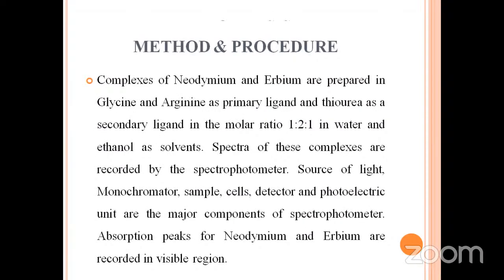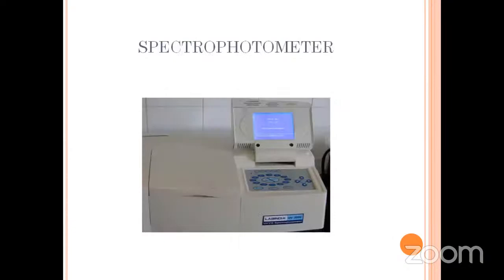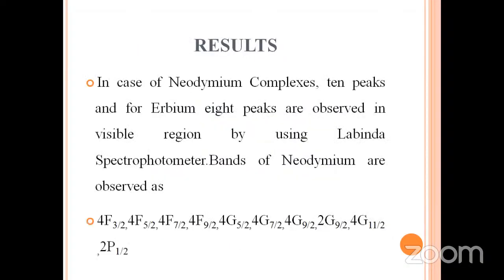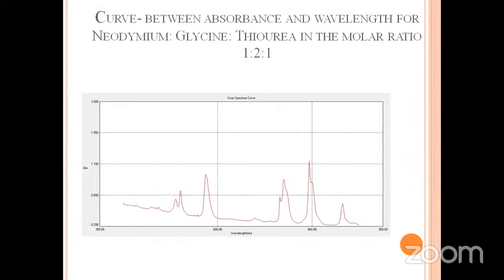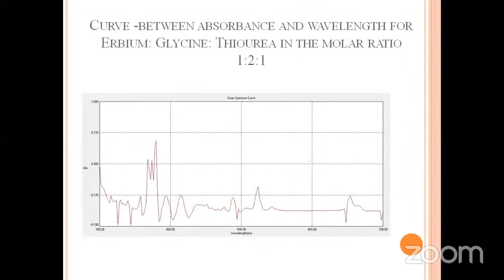And this is the method and procedure. With neodymium as the main rare earth, glycine as primary ligand, and thiourea as secondary ligand, I have prepared a solution in molar ratio 1:2:1. And this is the spectrophotometer with which I have taken the readings, the absorption curve. In case of neodymium, I got 10 peaks, and in case of erbium, I got 8 peaks. And these are the positions of the peaks. This is the graph of neodymium, glycine, thiourea in the molar ratio 1:2:1. This graph shows 10 peaks, and this is the graph for erbium, which shows 8 peaks.